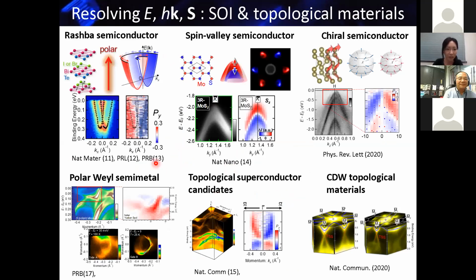Okay. And let me quickly go through these materials we've been working on. In these 10 years, we've been working on, for example, Rashba type semiconductor with this large spin splitting. This is a spin down and spin up. Okay. And also the spin-valley semiconductor with a spin up, down, which is coupled to this momentum. Okay. And recently we also worked on this chiral type semiconductor, which is tellurium. In this case, there is a spin polarization, which is coupled to the right-handed crystal and the left-handed crystal. The spin reverses when we look at the different chirality of the crystals. Okay? And there are many other topological materials we've been working on.